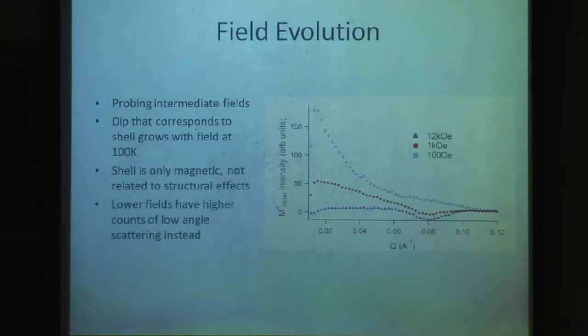Lately, what I've been doing is investigating how that shell evolves as we apply different magnetic fields, because we found that shell when we were at high field and temperature, but we want to know what happens when we're working at intermediate fields. And actually, we found that that shell is here shown in the purple. And that's true when we're at high field. But when we get to lower fields, such as the red, which is an intermediate field, that shell starts to disappear because the dip starts to decrease. Then when we go to a very low field, such as shown in the blue, that dip isn't even present at all. That shows that that shell that we had is a solely magnetic effect.